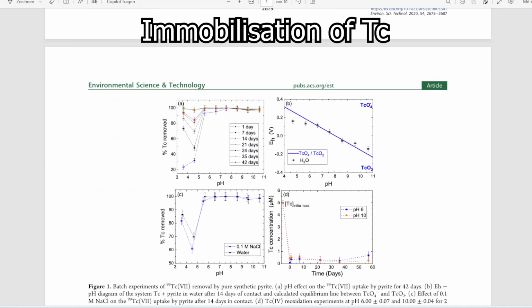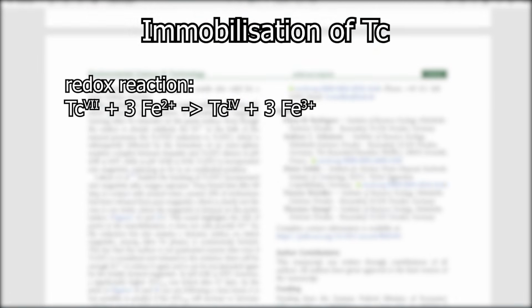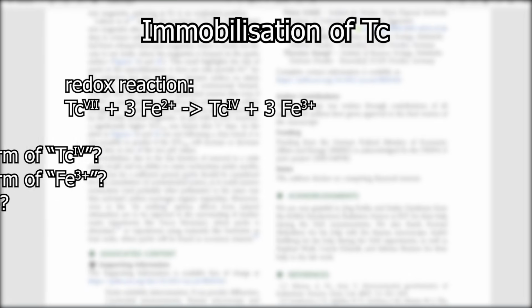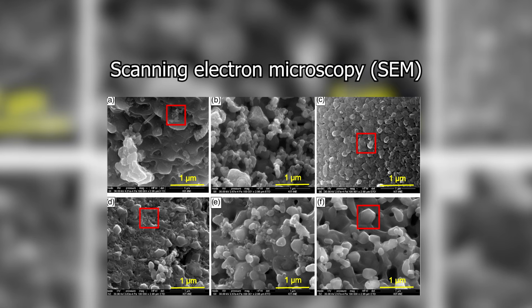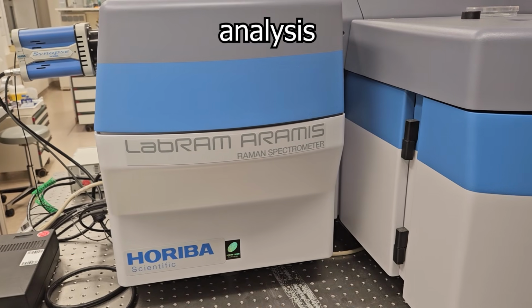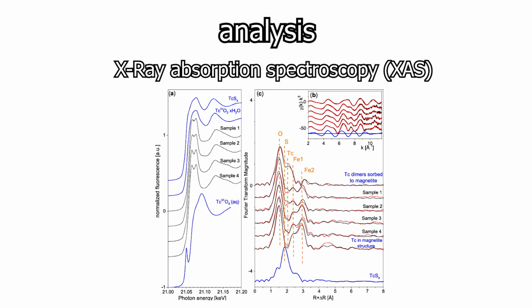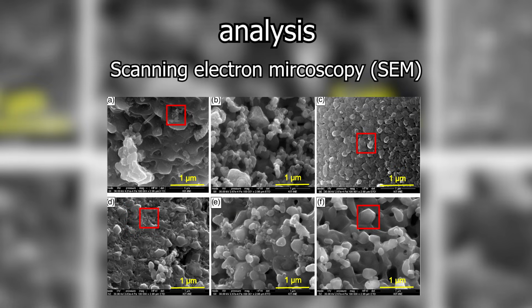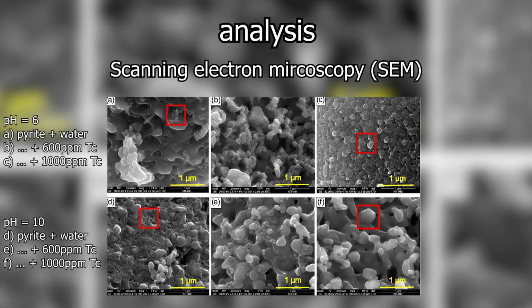Sure, I can easily write down the reaction equation like this. What does the structure look like now after sorption? To investigate this, SEM, scanning electron microscopy, Raman spectroscopy, and XAS, X-ray absorption spectroscopy were used. Now let's take a look at the SEM image. You can clearly see that the surface has changed.